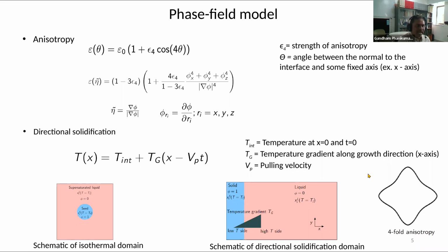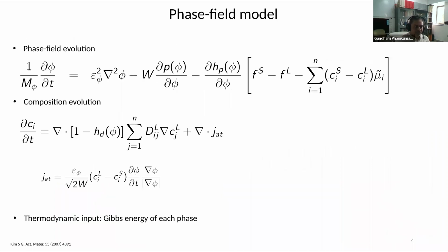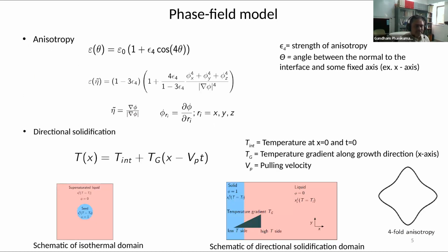Now, these solidification models have some parameters that are important for an additive manufacturing engineer to know. For example, the thermal field is modeled with the temperature gradient given here and the velocity of the laser heat source. When you change the velocity of the laser, or change the temperature gradient by preheating the powder bed, you are changing the thermal field during solidification. Once you change the thermal field, it affects the driving force, and therefore it also affects the microstructural formation. That we will see here.